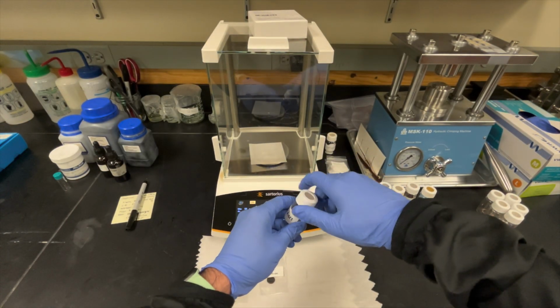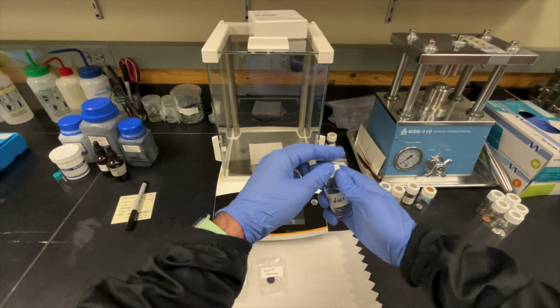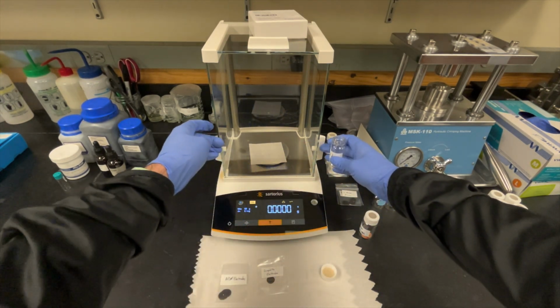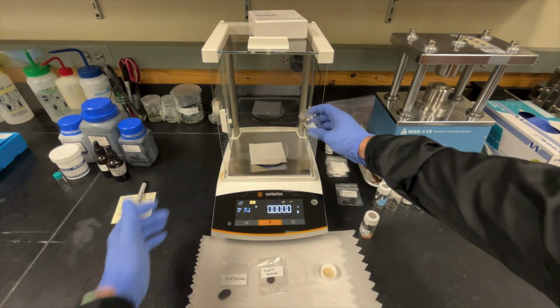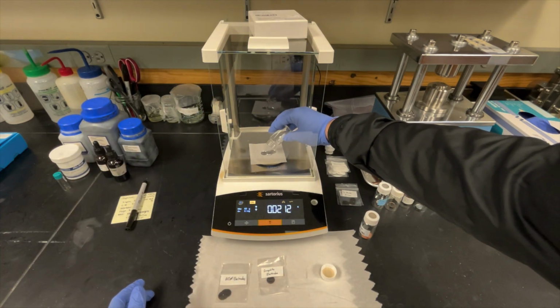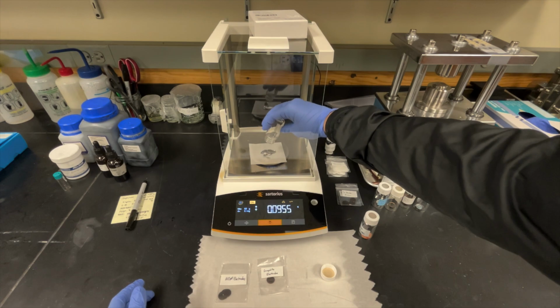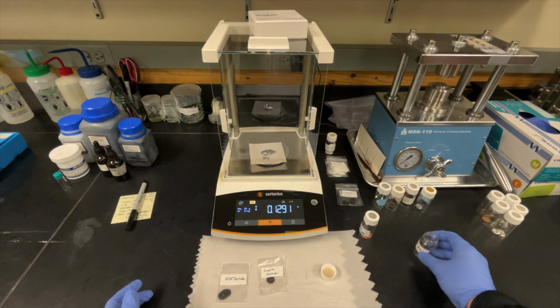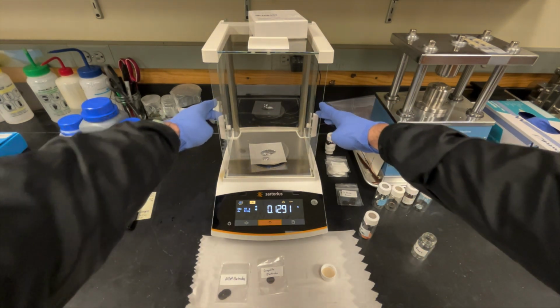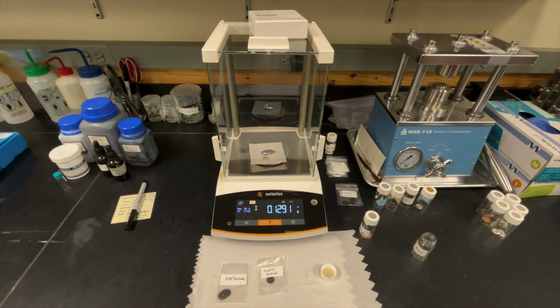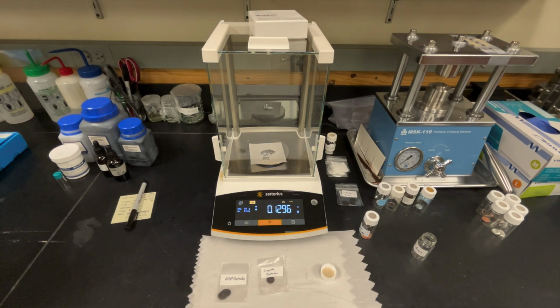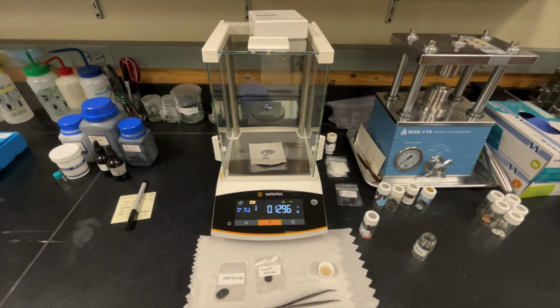Having now prepared both the NCM cathode and the graphite anode, we should now weigh them to determine how much active material is on the electrodes going into this battery. We can get this active material weight by determining the average weight of an aluminum or copper disc and then weighing the respective electrodes. Subtracting the weight of the disc from the electrode leaves the amount of total material, but we want the weight of the active material.